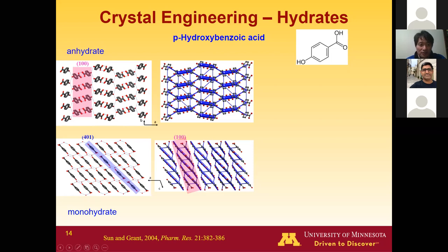If you consider this as the slip line, when you look at the hydrate, just visually you can see this may be a slip line. But when you look at the interaction energy, actually it's not the case. The molecules in the 100 plane interact strongly, but between these planes, that's a weak interaction. So actually this one is a slip line, 100 for the hydrate, but the corresponding slip line here has hydrogen bonds. You can see these interaction energies. So from this, you can see that for the hydrate, these slip lines can slide more easily. Therefore, it's more plastic,